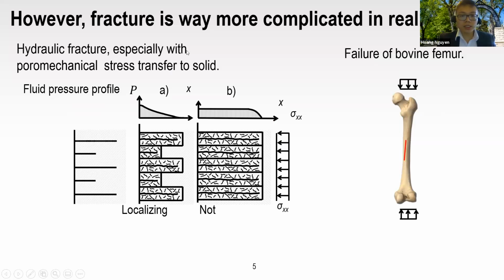Some situations are similar, for example in hydraulic fracture, especially when we couple the poromechanical stress transfer to the solid, when you have water come into the crack and fracture the internal band of the crack. So under the intact condition, the rock and other types of rocks and their surrounding environment are quite in hydrostatic stress or very close to hydrostatic stress.